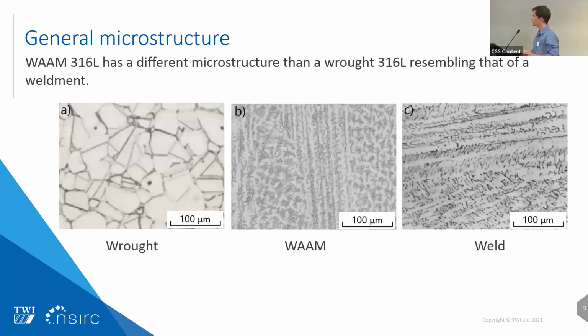It is interesting to compare that microstructure against other existing microstructures to give you an idea of where we are. Comparing with the wrought, we see it is really different. This is the microstructure of a 316 wrought alloy, where we have equiaxed grains and no delta ferrite in it. Here on the right-hand side is the microstructure we would have for a conventional 316L weld.